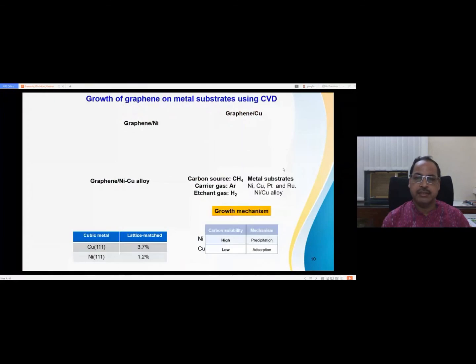So in the following slides, we will first see the CVD growth of graphene on the metal substrate. You can see the growth mechanisms of graphene, hexagonal boron nitride and the TMDs are different. For example, graphene mostly grows on the metal substrate. Now some people grow it on insulating substrates, but the yield is very low. Why a metal substrate? Because the mechanism is very different, either by precipitation or by surface adsorption.